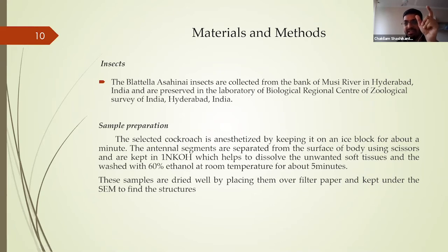We have taken a cockroach and anesthetized it, and we have selected particular antennal segments and separated them. Those segments were treated with potassium hydroxide, and after that we washed them with ethanol. Then we dried the samples and examined the structure using a scanning electron microscope.